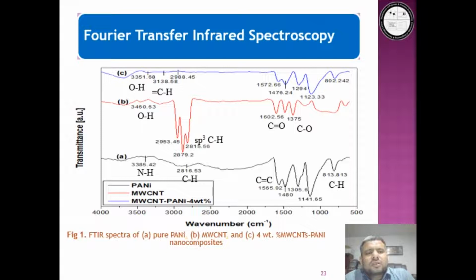In the Fourier transform infrared spectroscopy, you see the figure, the spectrum of pristine PANI or polyaniline, a peak at higher wave number of 3385 is attributed to the stretching of the NH group. Similarly, the bands at 2816 are due to the unbalanced CH expansions of the aromatic ring, while peaks at 1565 correspond to the C double bond stretching. Thus, the characteristic peaks at 1141 and 813 are assigned to in-plane and out-of-plane bending vibration of aromatic CH respectively.